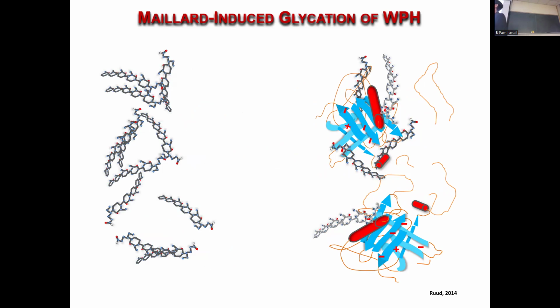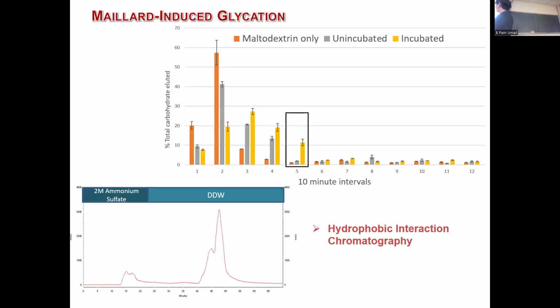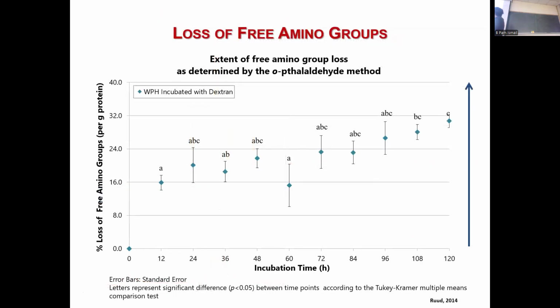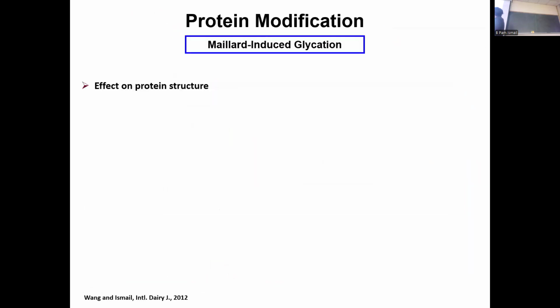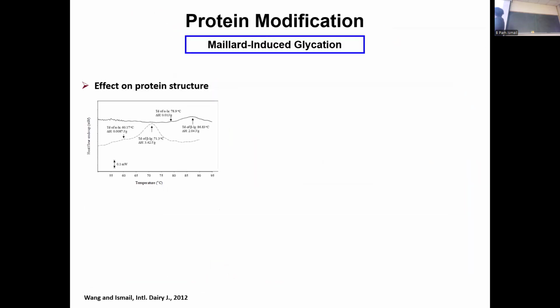So it should have above 80% protein. We need to remove the free unreacted carbohydrate, and we usually use hydrophobic interaction chromatography. And we confirm at which point we get our protein that is glycated. It has some carbohydrate in it, obviously. And we make sure that at this time point we get the protein, and the carbohydrates that are not reacted are coming out in the initial fractions. So that is essential. We look at the loss of amino groups at different time conditions.